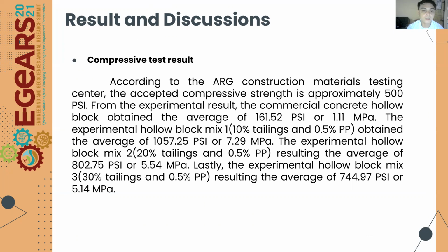The experimental hollow blocks mix 1 with 10% tailings and 0.5 polypropylene plastic obtained the average of 1057.25 psi or 7.29 MPa. The experimental hollow blocks mix 2 with 20% mine tailings and 0.5 polypropylene plastic resulted in the average of 802.75 psi or 5.54 MPa.